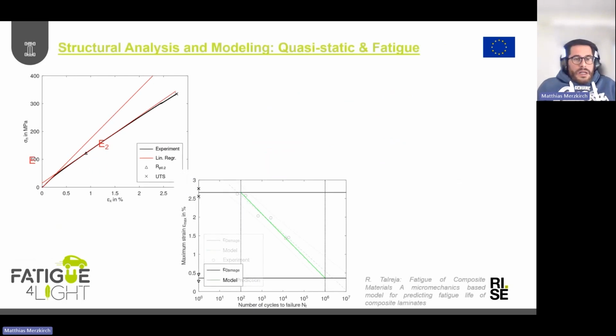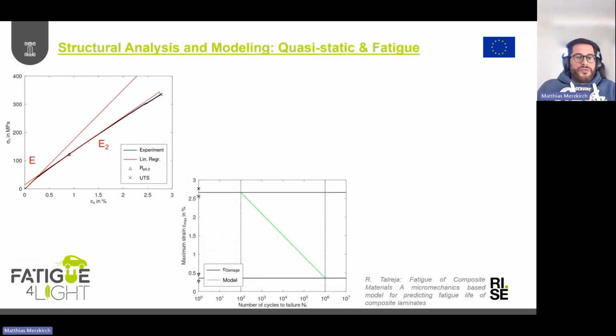So why are we using that? Now comes a rough estimation in order to determine the fatigue, in the Fatigue4Light project. We're using the stiffness, or the slopes, of those two separate areas. The first one is the Young's modulus, determined at low strains. Here we also see this kink, which is correlated to the microcracking. And we have the second slope here. Here, just as a reference, the Rp0.2 value.